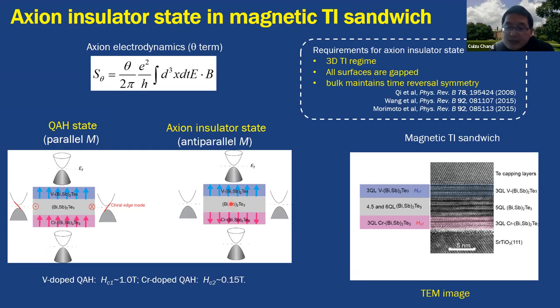As I just introduced in the previous two slides, the quantum anomalous Hall effect has already been realized in chromium doped and vanadium doped magnetic TI systems. The chromium doped and the vanadium doped quantum anomalous Hall systems have different coercive fields. So we decided to glue them together into this kind of sandwich structure.